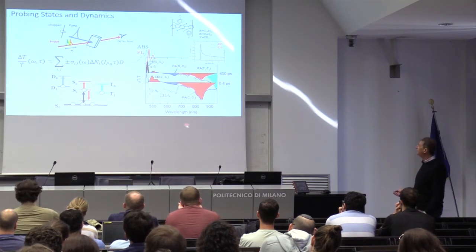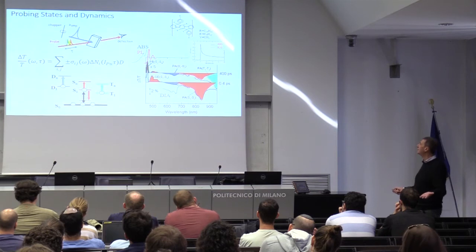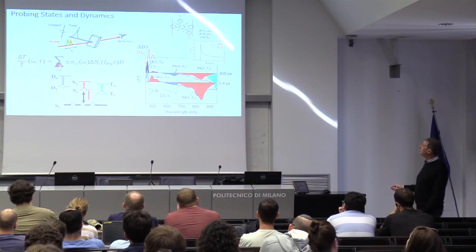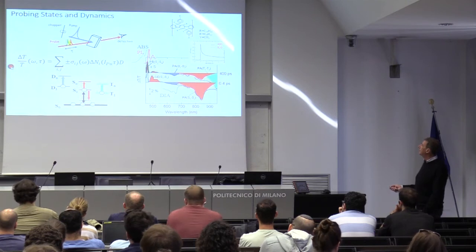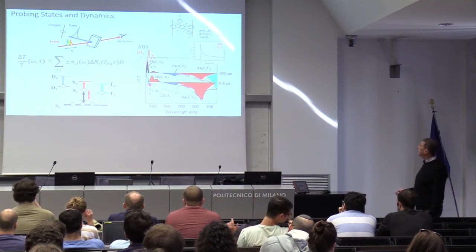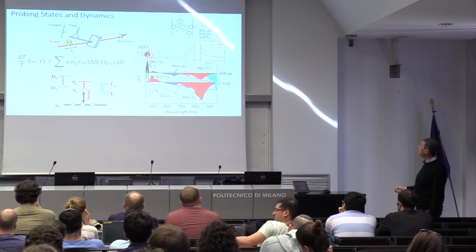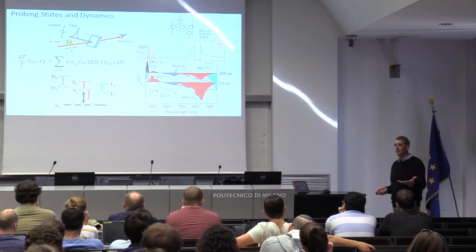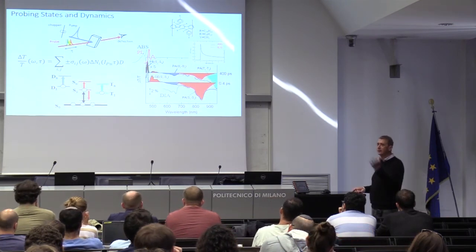Now here you see everything. In this spectrum, there is everything you want to see. So you pump the material. Of course, the formula that we use to interpret is this that I told you. And you see, we pump and we generate singlet, triplet, and doublet, everything. So we see bleaching. Here it is, a positive signal. There is a peak positive where the material is absorbing. That means the material is less absorbing from the ground state, because it's photoexcited, so there are populations in